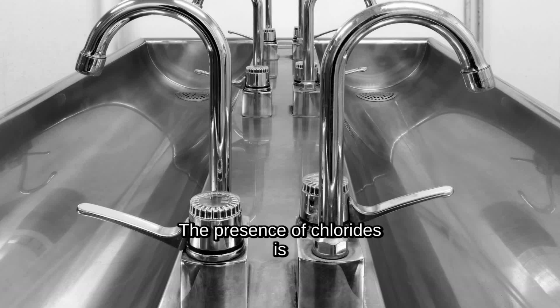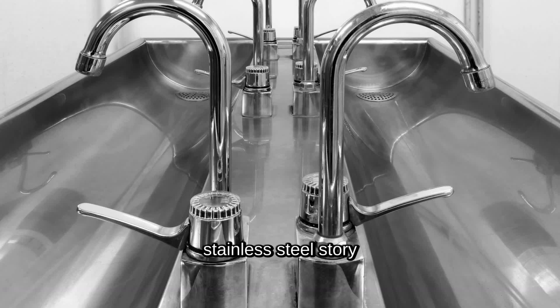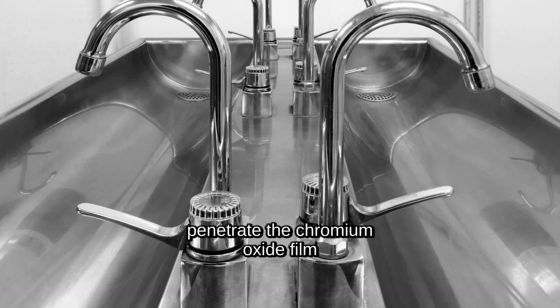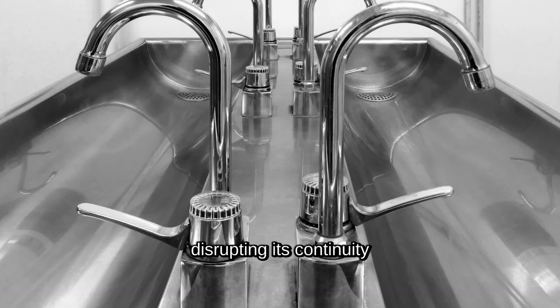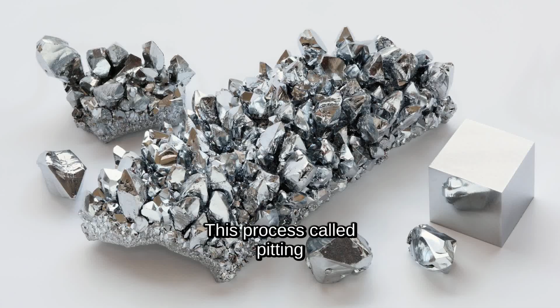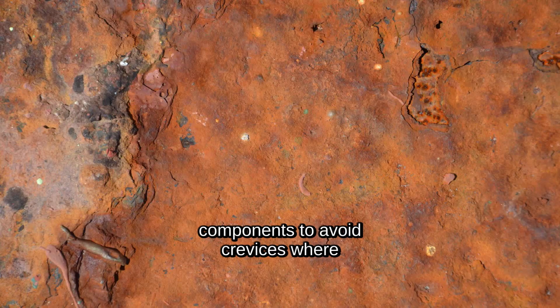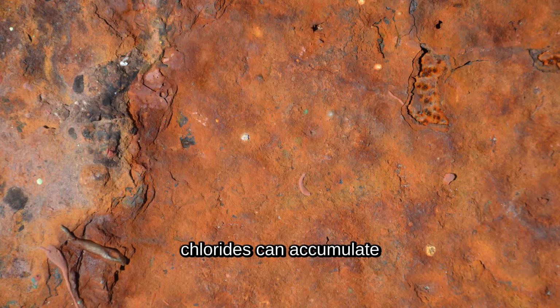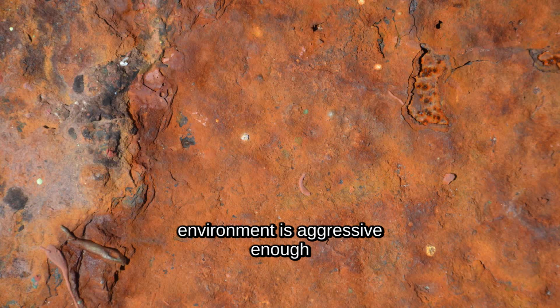The presence of chlorides is a crucial weakness in the stainless steel story. In coastal areas or inside swimming pools, chloride ions can penetrate the chromium oxide film, disrupting its continuity. This process, called pitting corrosion, creates tiny, localized holes that can grow rapidly, eventually leading to structural failure. Engineers combat this by selecting higher molybdenum alloys, applying protective coatings, or designing components to avoid crevices where chlorides can accumulate. Even the most resistant stainless steel can succumb if the environment is aggressive enough.